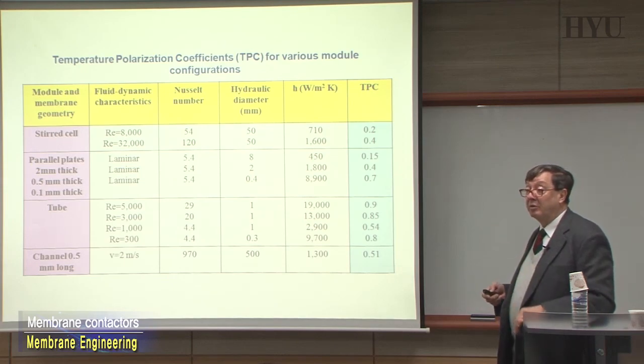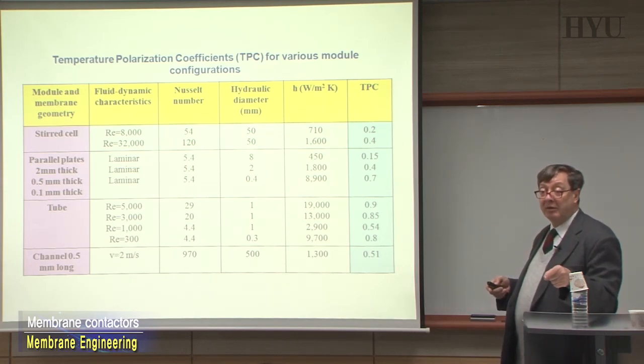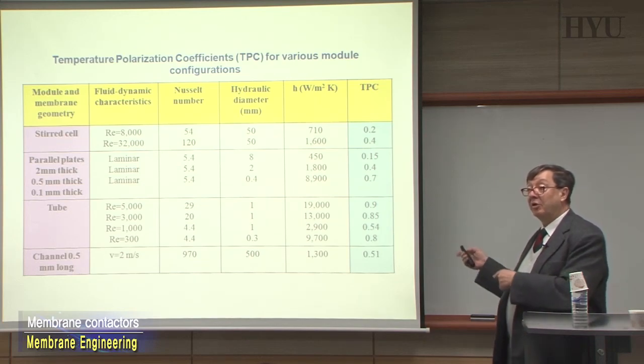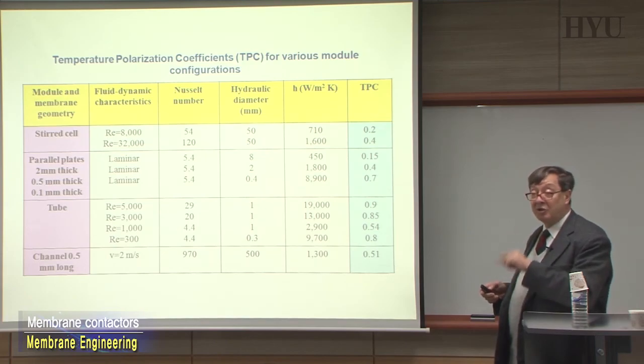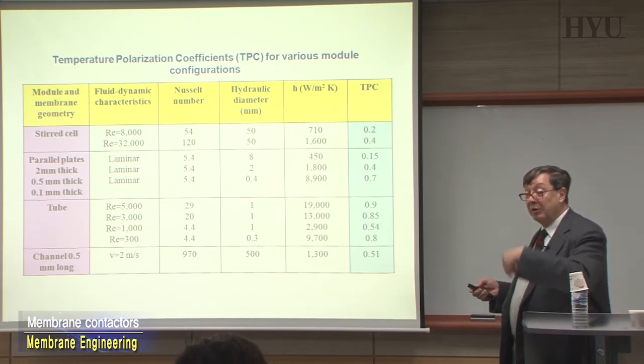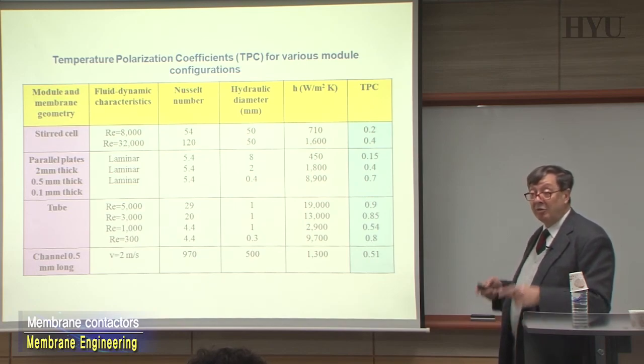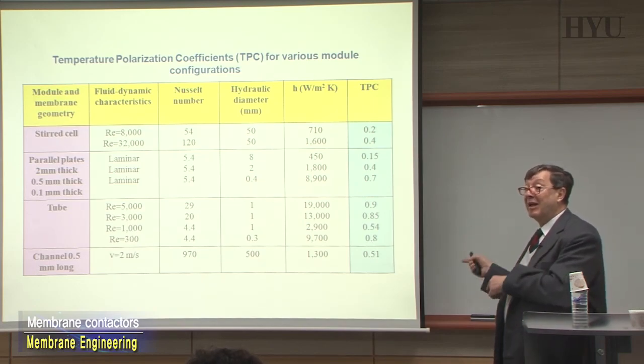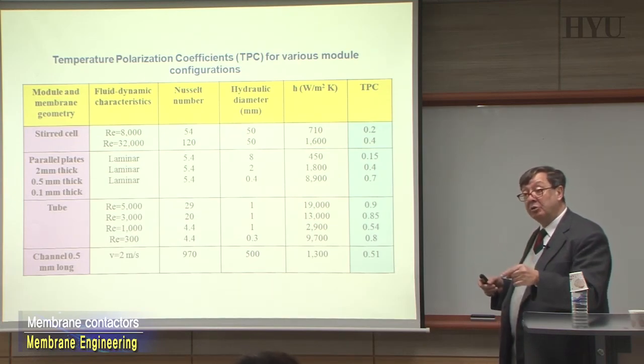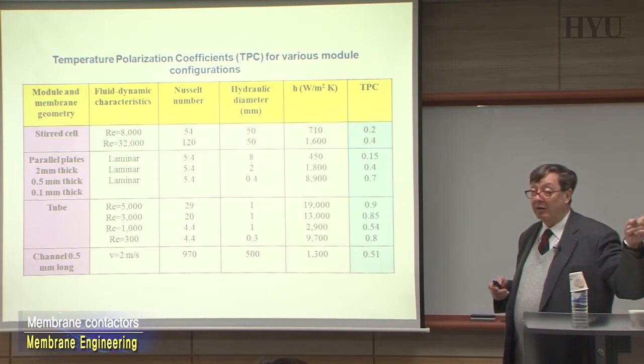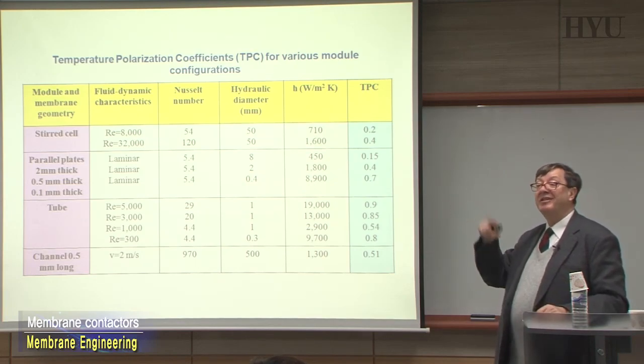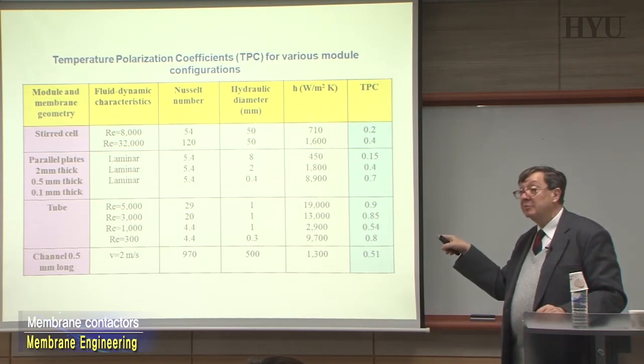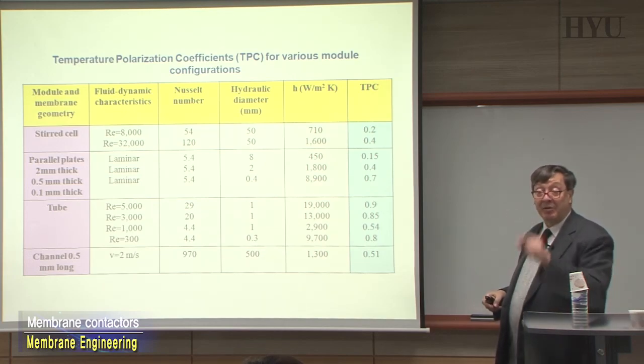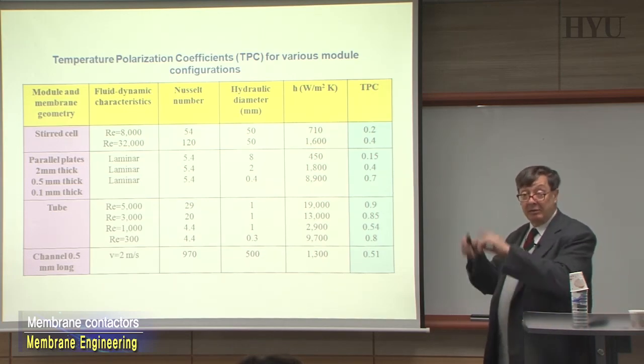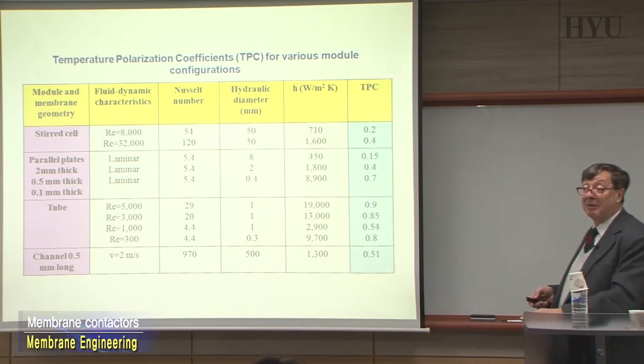And you will find in your notes, if you don't take care of the concentration polarization, seawater is going across your membranes and you are assuming that there is a pore. It's not. It was a wrong operation that you have been carrying on. You are not keeping control of the concentration at the interface. So the membrane was working with 99.9% rejection against a solution that was not seawater, 0.5 molar, but was the interfacial concentration that was 3 molar. And with 3 molar, seawater is going across with 99% rejection. Same story here as final results. So you have to keep control of thermal polarization.